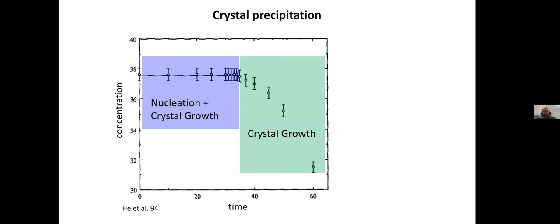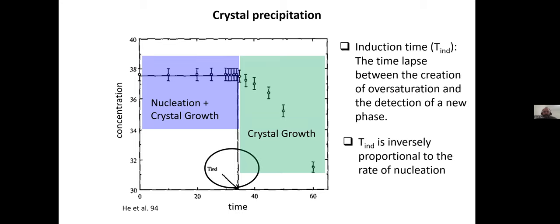Now, the last definition to remember for the rest of the talk: if I look at a system that's oversaturated, there's some time difference between the creation of the oversaturation and the time I can detect the creation of the crystals. During this time, the system is dominated by nucleation. The crystals that form do grow. However, there's not a lot of surface area available for growth, so I don't detect the change. The time until I can detect the change is called the induction time, and it is inversely proportional to the rate of nucleation. Basically, the faster the crystals are formed, the shorter the induction time. It takes me less time to detect them.